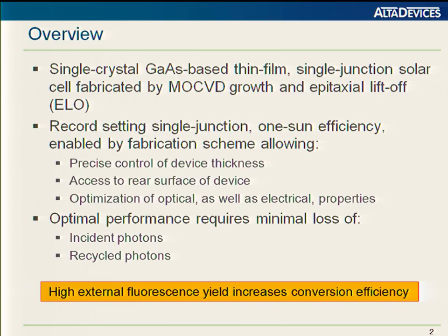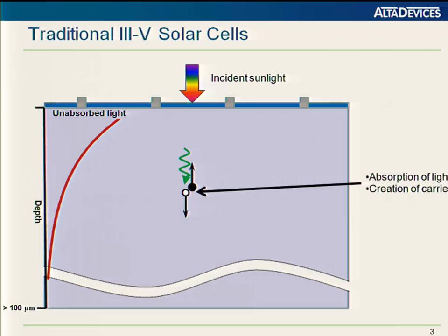And I hope to convince you by the end of the talk that high external fluorescence yield, that's the emission of light from the solar cell itself at open circuit, in this kind of device is an indicator of high voltage within the cell from high carrier concentration. So most of this talk is going to be from a pretty high level. I'm going to show conceptually how we think about it without going into the detail. Hopefully I can bring you along all the way to the end without losing too much of the audience that way. Shown here is a cartoon of a thick III-V solar cell.